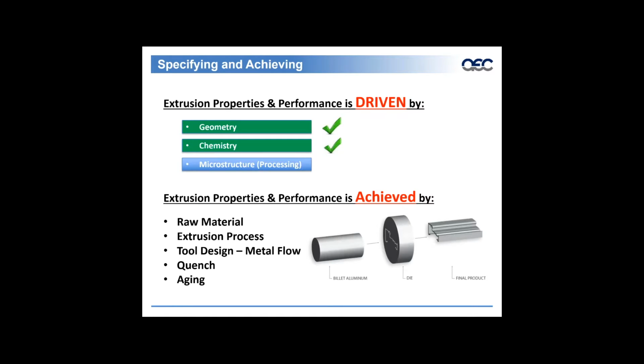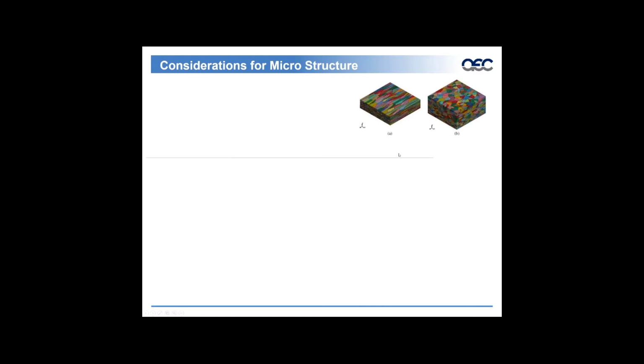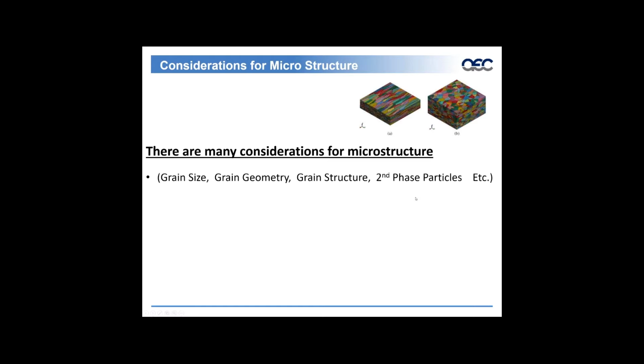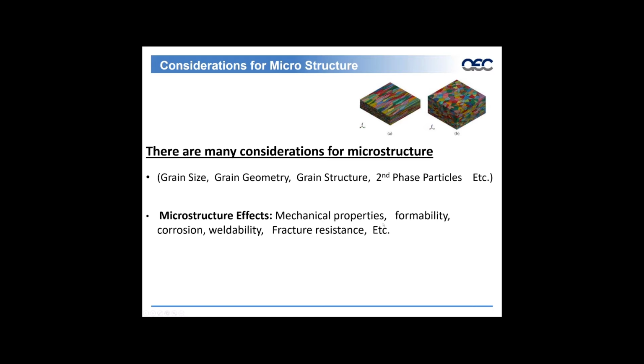So that's a little bit about chemistry, and now we'll talk a little bit about microstructure and processing. There are many considerations for microstructure: grain size, grain geometry, grain structure, second phase particles. It's a fairly long list. Microstructure affects our mechanical properties, formability, corrosion resistance, weldability, and fracture resistance. Microstructure depends on the alloy composition and the extrusion process itself.